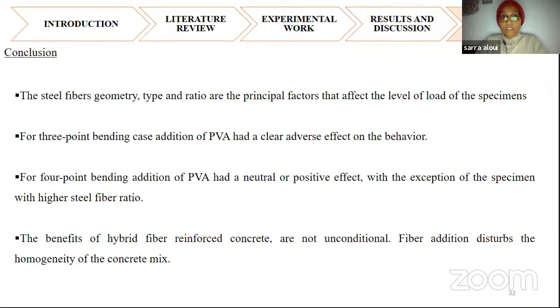The steel fibers geometry, type and ratio are the principal factors that affect the load level of the specimen. Like we can see here, the short steel fibers have less maximum capacity. But the specimens with the long steel fibers have a higher maximum load. Also the type: a specimen with double hooked ends has a higher maximum capacity. Or the ratio: specimen SA4 has a higher amount of steel fibers, so it has a higher maximum capacity.